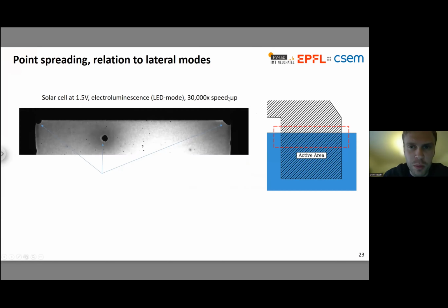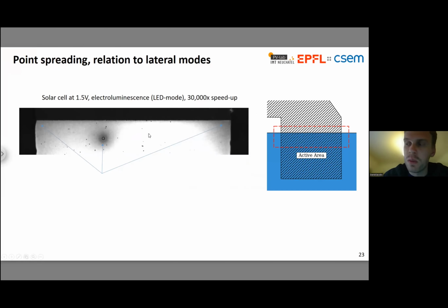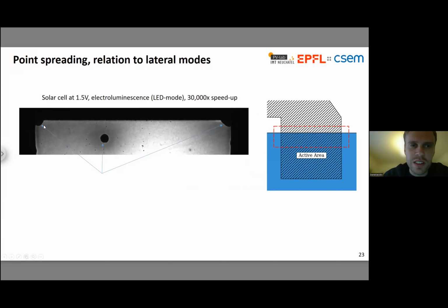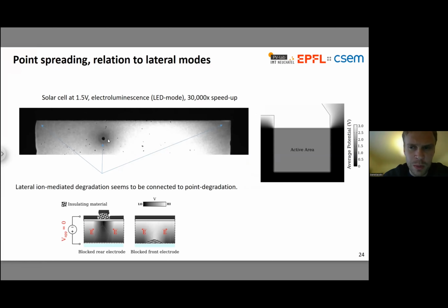So this has been sped up quite considerably. It was a test that went over about 50 hours. But it's very interesting to see that this degradation at the corners strongly resembles what's happening at the point of contamination. So what's going on with the corners?